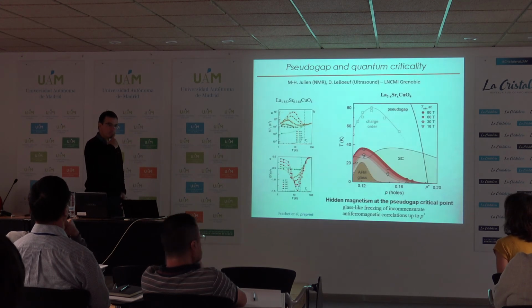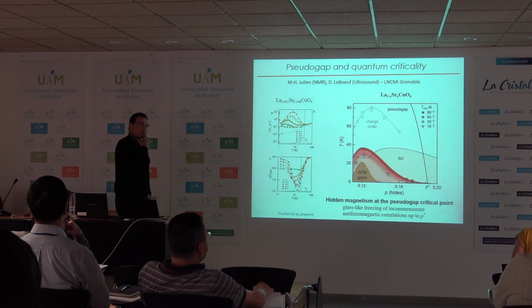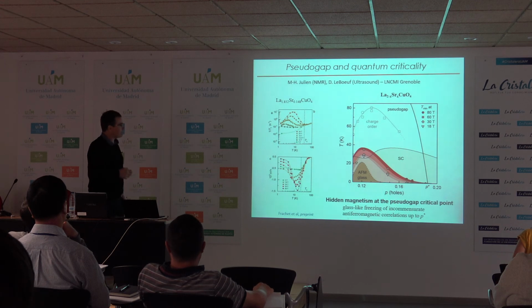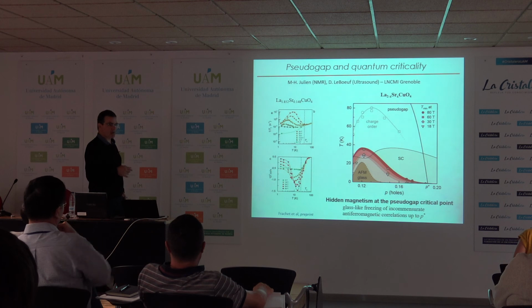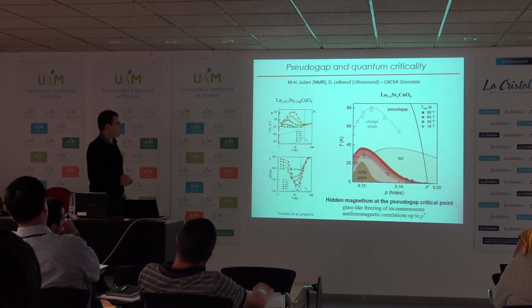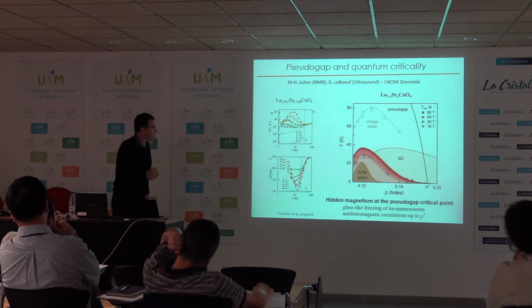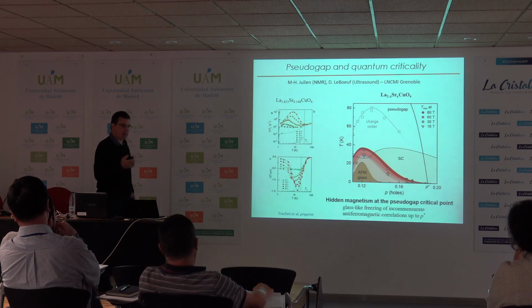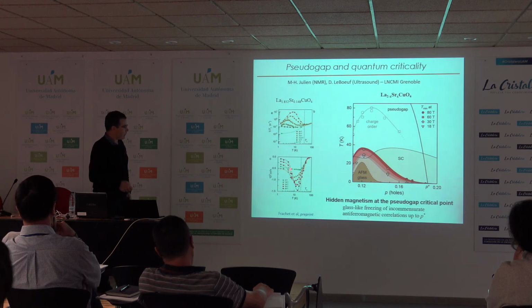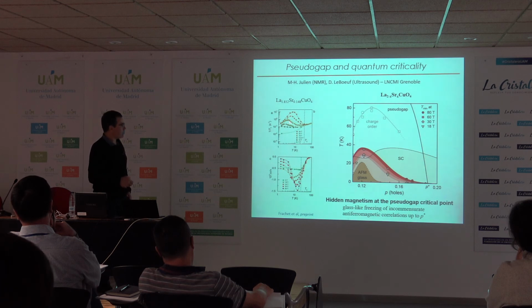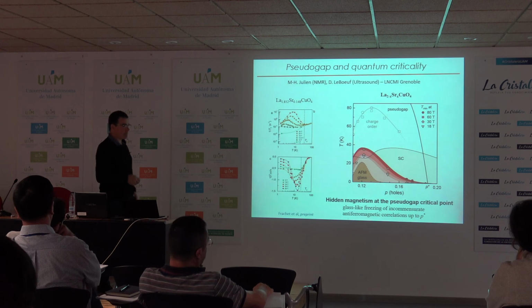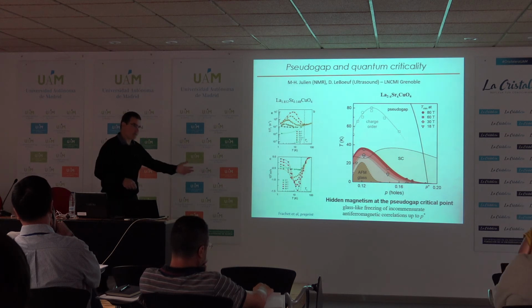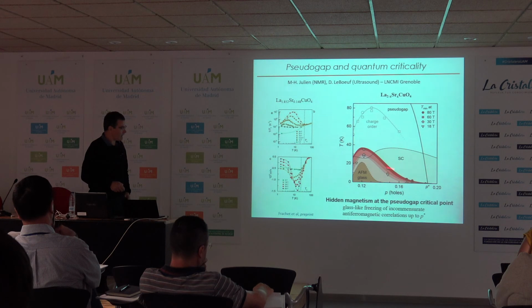Does it become less glassy under magnetic field? Glassy is defined by the fact that it's not well ordered, you don't have a sharp transition. They cannot yet perform an NMR measurement in pulsed magnetic field. It's possible, but very difficult. So basically, they measured a sample where it's well known, and they make a parallel between NMR, which shows a maximum of the 1/T1 at the glassy transition, which corresponds to a minimum in the sound velocity measurement. And after that, the sound velocity has been measured in pulsed magnetic field, because we can perform sound velocity in pulsed field, and this minimum extends up to this point.